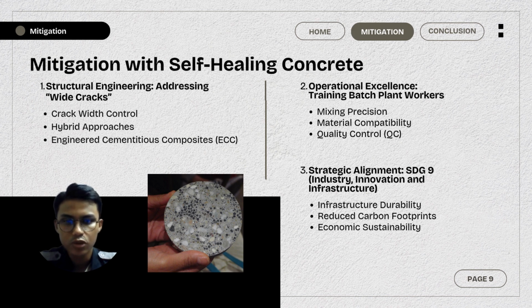Firstly, crack width control. Use structural design to limit the crack width, for example adequate reinforcement ratios, so that they fall within the self-healing range, typically 300 micrometers. Secondly, hybrid approach. Combine structural reinforcement with autonomous agents, which is micro-encapsulation or vascular system that can be triggered once the crack width is controlled. Thirdly, engineered cementitious composites, ECC. Integrate materials that promote multiple microcracking instead of a single large structural crack, making the damage more manageable for the healing mechanism.